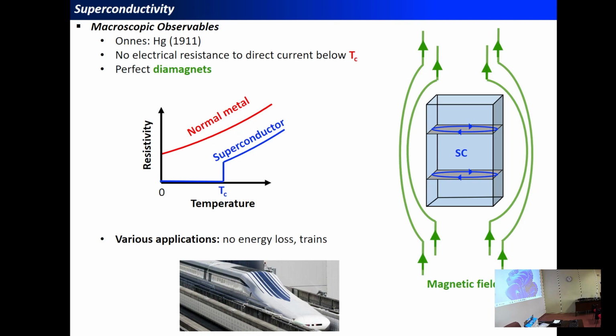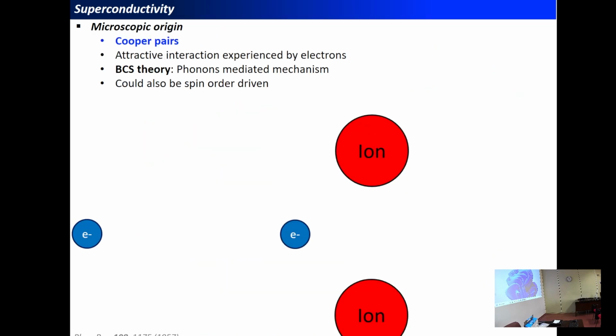At the microscopic level, how can we explain superconductivity? Since the beginning, it's explained in terms of Cooper pairs, where electrons are put together. For that, we need an attractive interaction experienced by electrons. In the original papers of the BCS theory, it's proposed that it is a phonon-mediated mechanism.